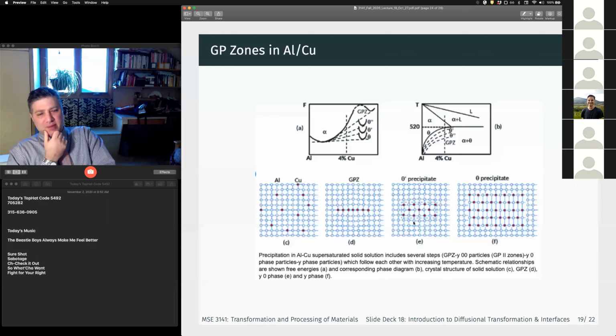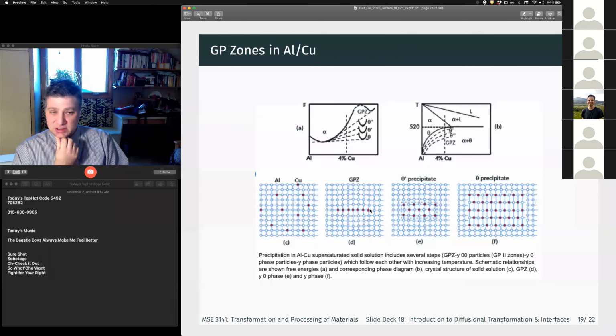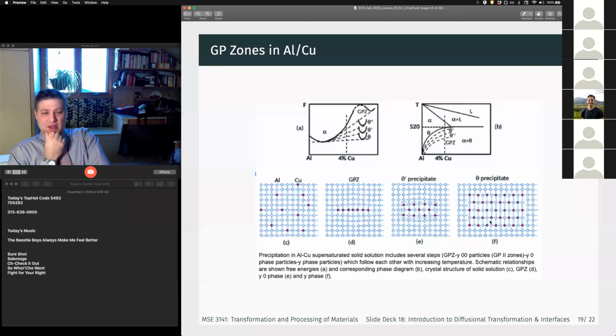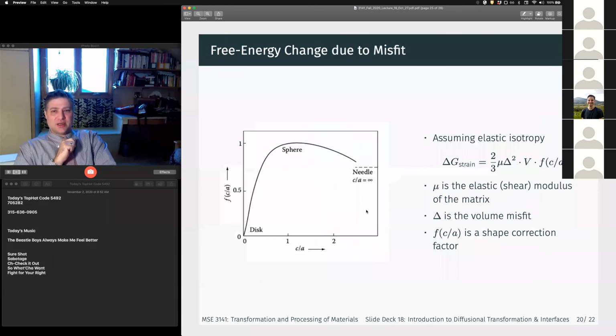So often we have metastable things that appear because we can get a gradual lowering of the energy of our system. If we waited until we had enough driving force to nucleate this theta, it would essentially never happen. So we can nucleate these GP zones homogeneously, right? From the GP zone, we can nucleate the theta double prime and theta prime heterogeneously from these GP zones. And then the theta can nucleate from the theta prime, right? And we'll talk about that in much more detail later. First, we need to talk about the theory of nucleating secondary phases in a solid homogeneously, and you'll see it's really very similar to nucleating solid from a liquid.